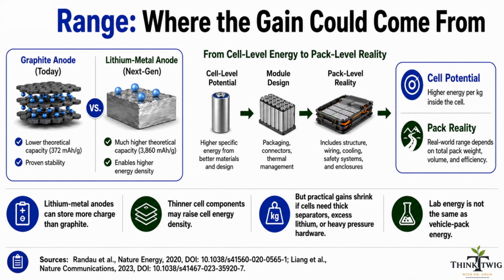Again, it sounds perfect, but laboratory cells can be misleading. Many use thick lithium foils, very thick. Some studies use more than 200 micrometers of lithium, and practical cells may need something closer to 20 micrometers. Why does this matter? The extra lithium helps the experiment. It hides some losses. It improves cycling, but it also adds weight, takes space, and lowers the real energy advantage. So, a higher number in a small lab cell does not automatically mean longer range in a real car. A cell is not a pack, and a pack is not just active material.